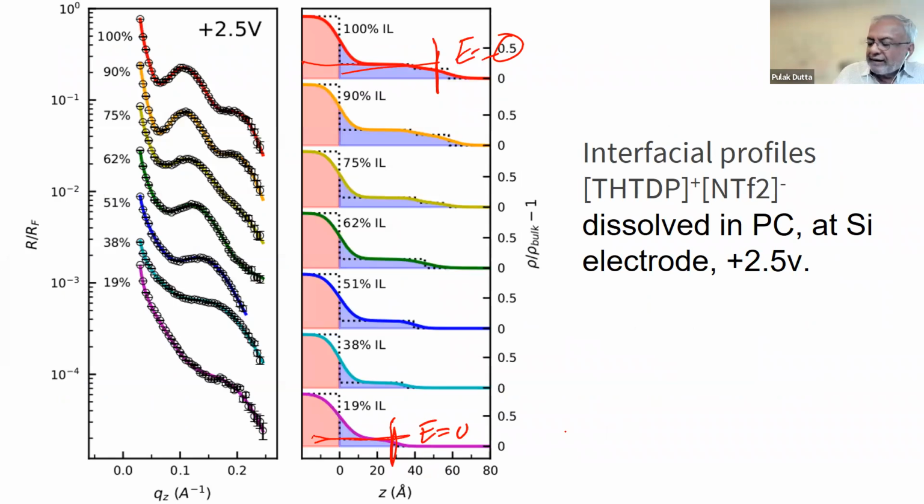Well, you can't make that argument here because it's about 80% anions and 20% cations. So 20% of the cations could possibly be neutralizing 20% of the anions, but that still leaves 60% to be charged. And yet these charged particles are not neutralizing the electric field. The way we know that is that this pileup is much longer.